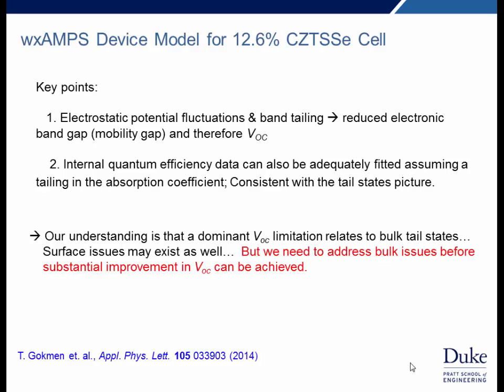Rather, we're introducing these electrostatic potential fluctuations by the introduction of a mobility gap which is smaller than the optical gap in the material, or the band gap that we get from the EQE. And this is what's responsible for the reduction in the open circuit voltage. This band tailing also accounts for the tailing in the absorption coefficient that we observe. And so again, this points to the fact that bulk tail states are important in terms of trying to reduce the open circuit voltage deficit.